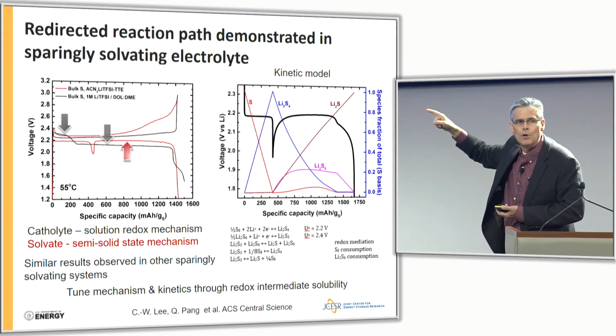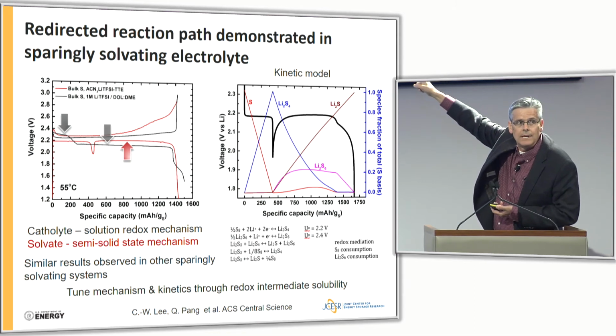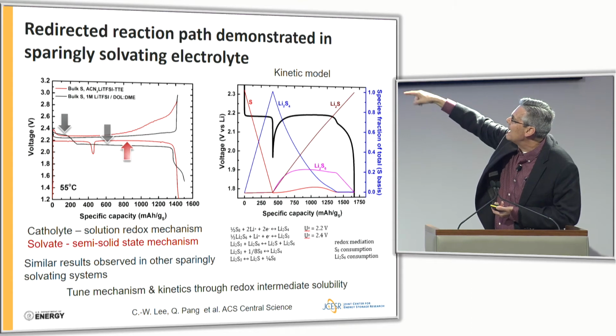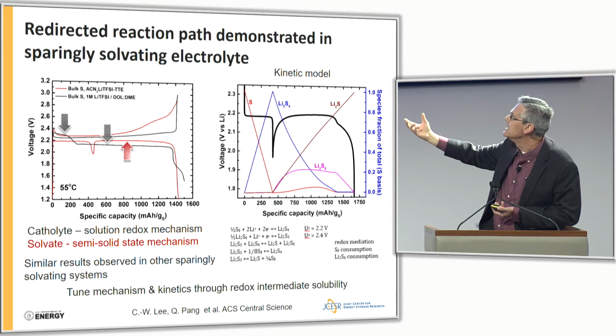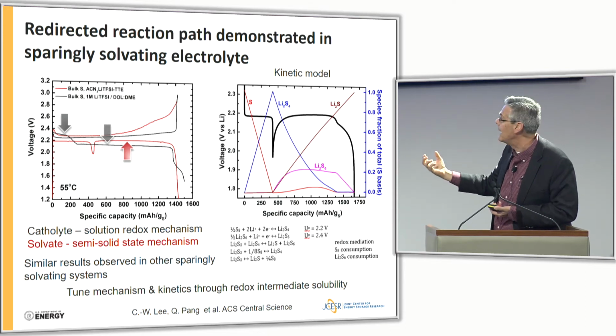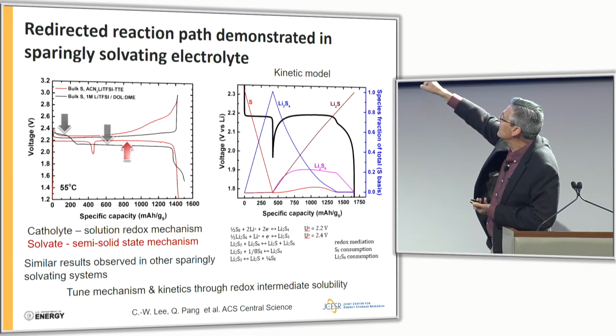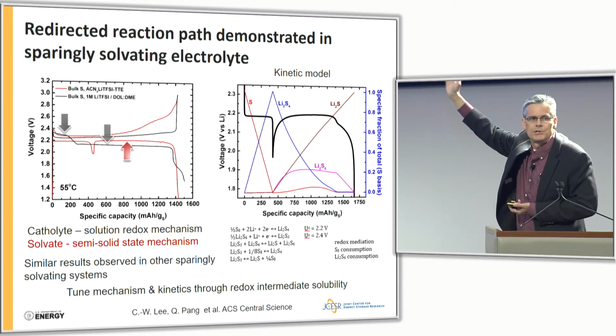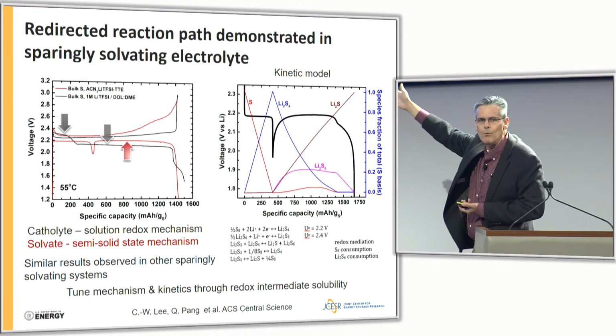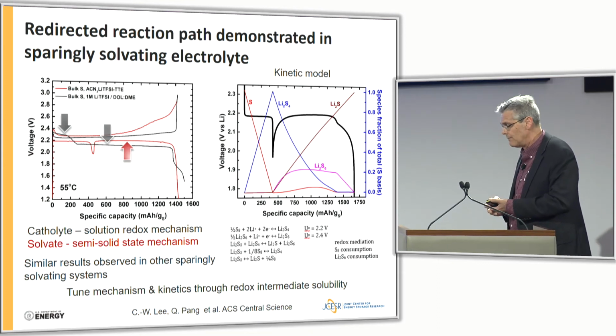Eventually, where the dip occurs is an overpotential, where we've essentially produced our maximum amount of the S4 2-. We have to switch the reaction now. We have to drive some other reduction process, and now we're producing a critical mediator. We think it's Li2S6. It could potentially be the radical anion S3 minus, or excuse me, S3. And the bottom line is that that plays a critical role in that fuchsia curve, rose-colored curve, right, that is showing constant presence, right? And disproportionation is also working at the same time because we're starting to produce sulfur again, right? So we have this mixed potential that's about 10, 20 millivolt higher than the first potential.